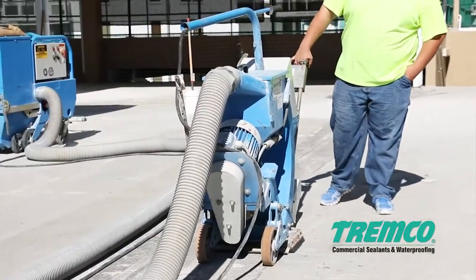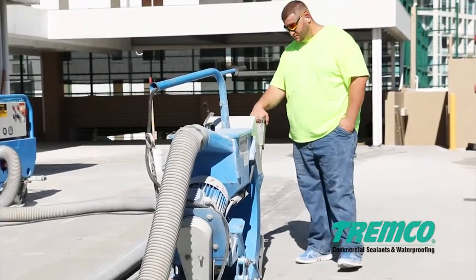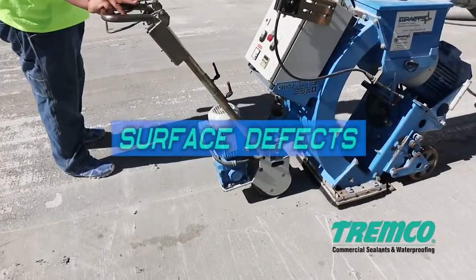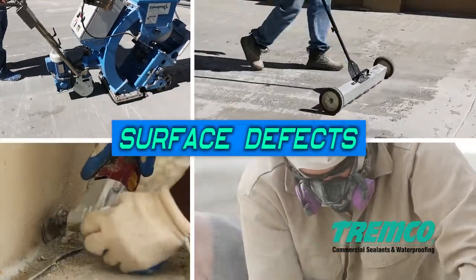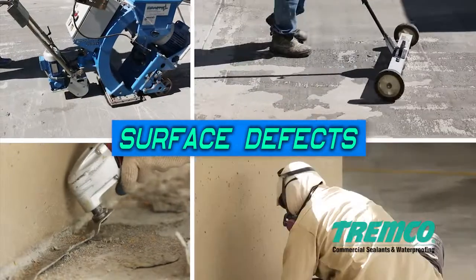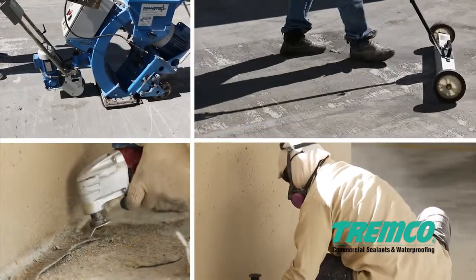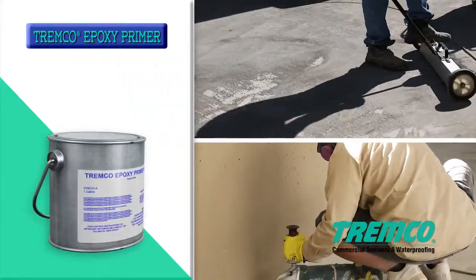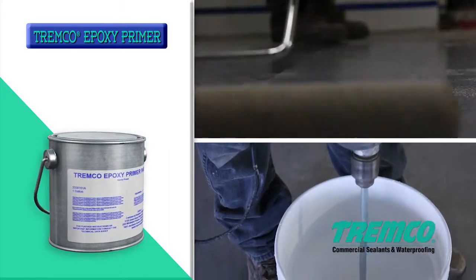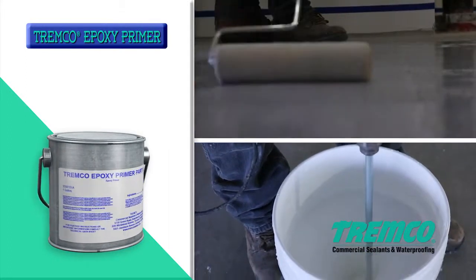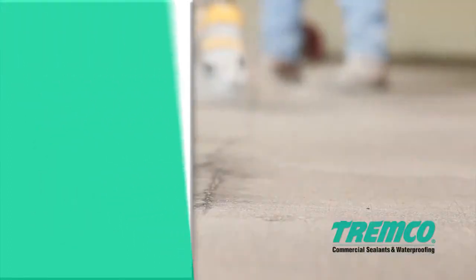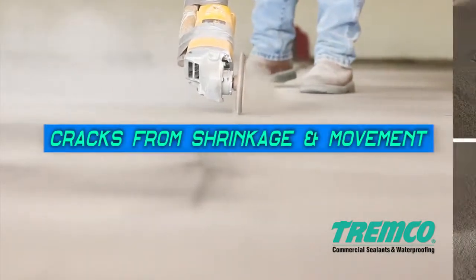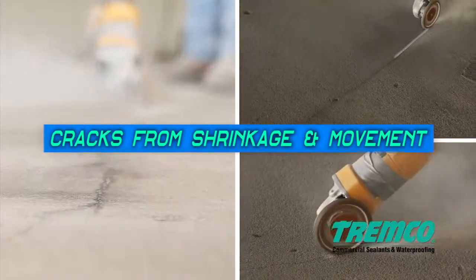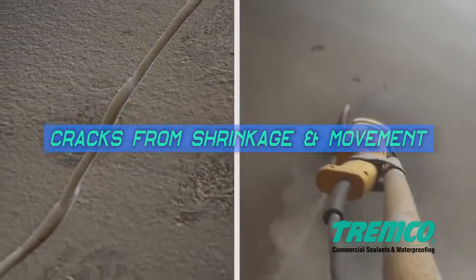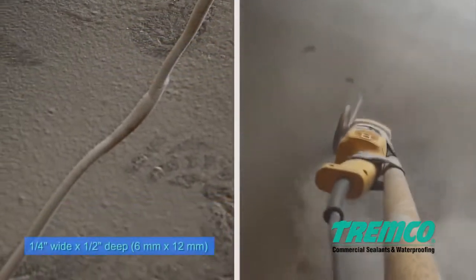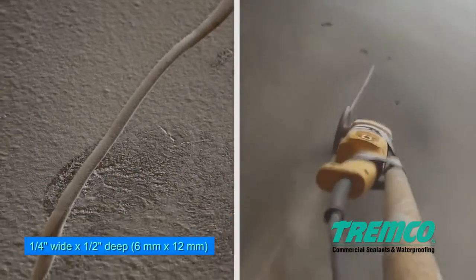Surfaces must be free of defects that may telegraph and show through the finished coating. Surfaces that are rough, such as fins, ridges, exposed aggregate, honeycombs, and deep broom finishes, must be leveled and made smooth by applying a coat of Tremco Epoxy Primer, sanded, or equivalent filler material. Shrinkage cracks that are 1/8 of an inch or 3 mm wide and structural cracks from building movement regardless of width should be ground out to a minimum 1/4 inch wide by 1/2 inch deep.